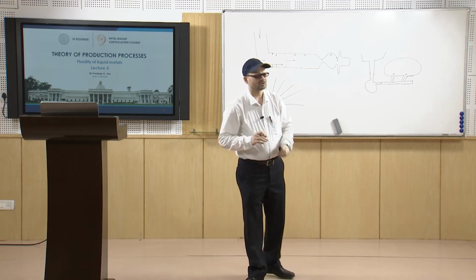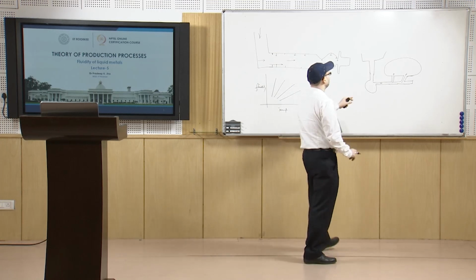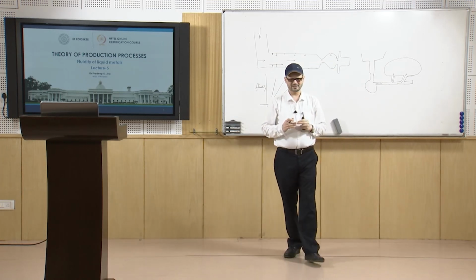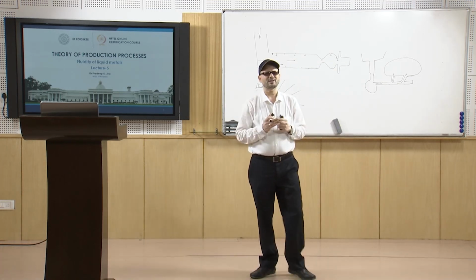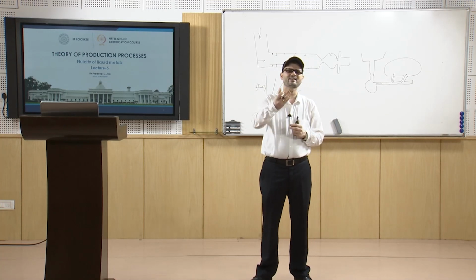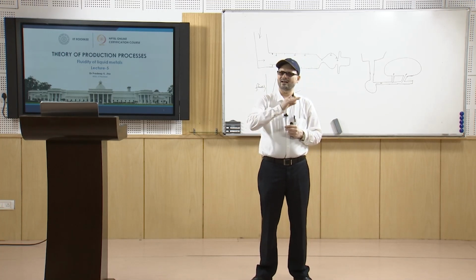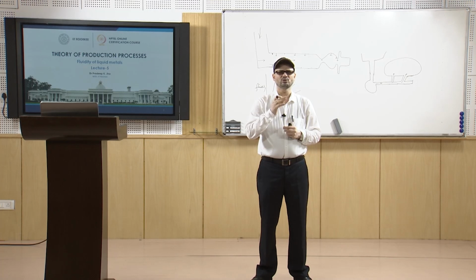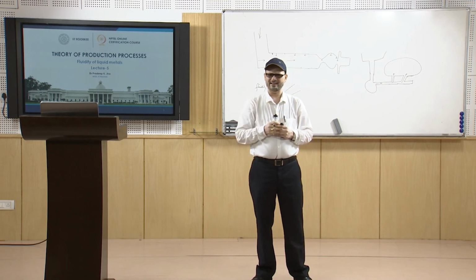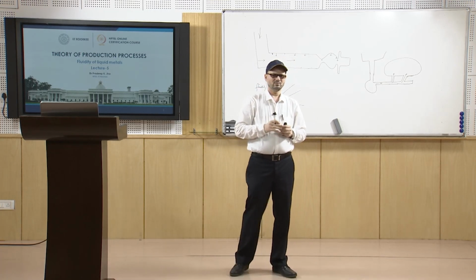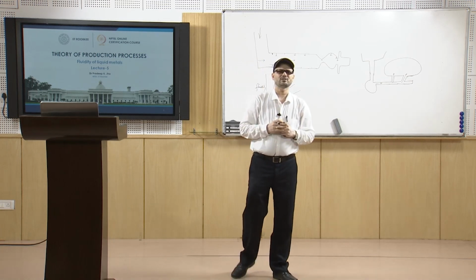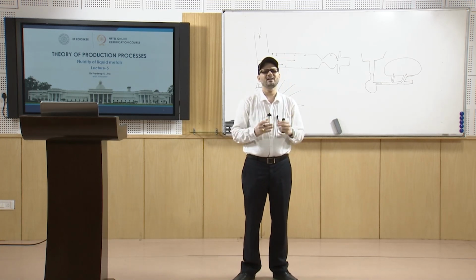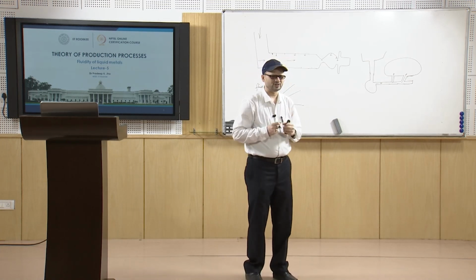Minimum frictional loss. For that, basically, we use the surface in such a manner that you have minimum friction. Like, if it is sand grain, you should use the mold wash, you should use the fine grain sand so that you have minimum frictional losses. Similarly, you have energy losses.